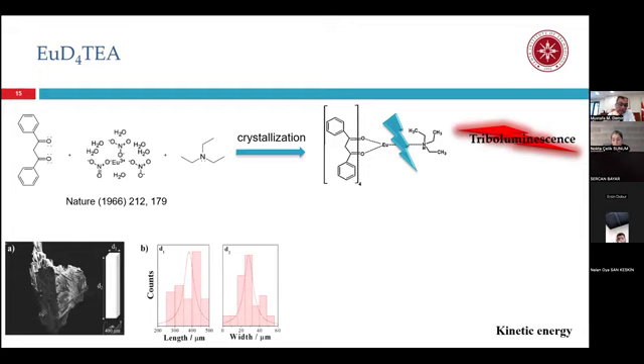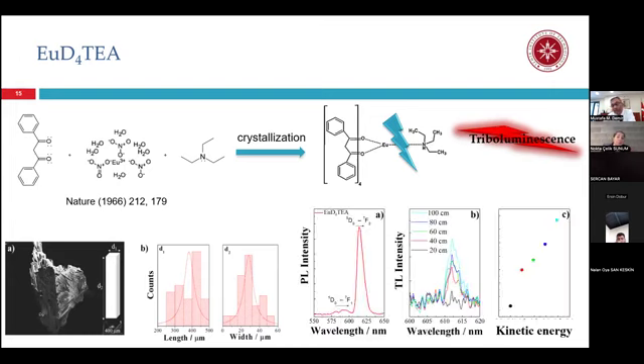We see a representative electron microscope image of the crystal on the left-hand side. The crystal is a rectangular prism. The length is 400 micrometers and the width is 30 micrometers on average. We have photoluminescence of this material in solution; it's quite a nice signal. In the middle, we see the triboluminescence spectrum of the particle. We have free fall of the ball from 20 centimeters up to 200 centimeters. As the height increases, the intensity of this emission increases. It shows that it's a very promising material for mechanosensor applications.